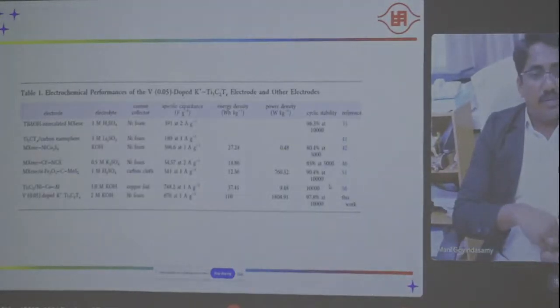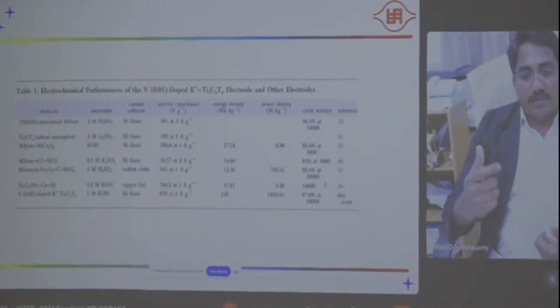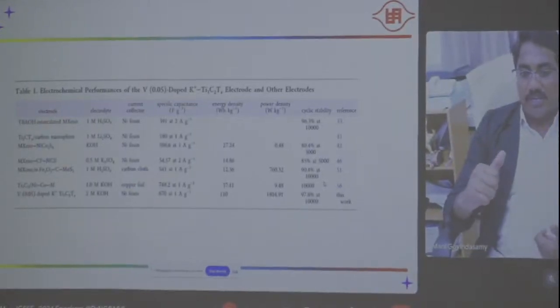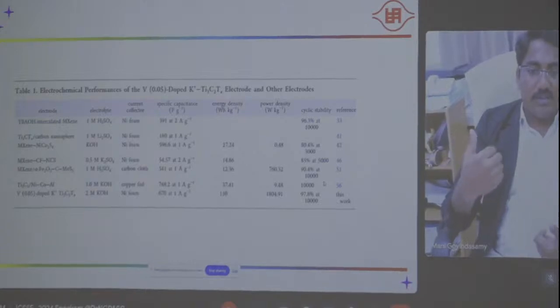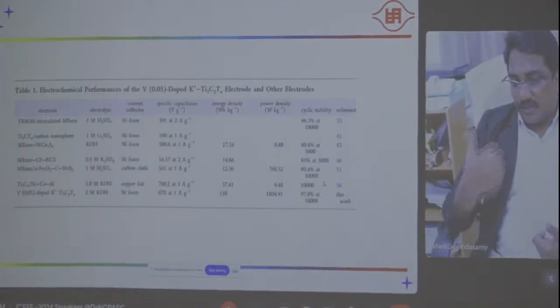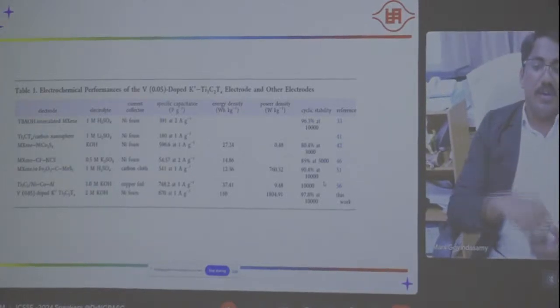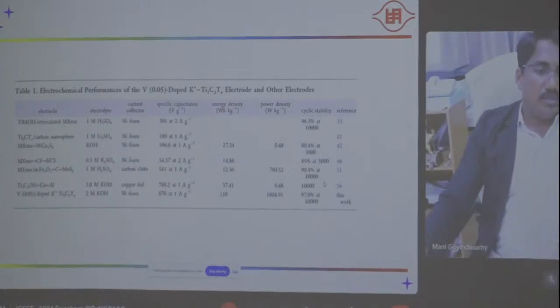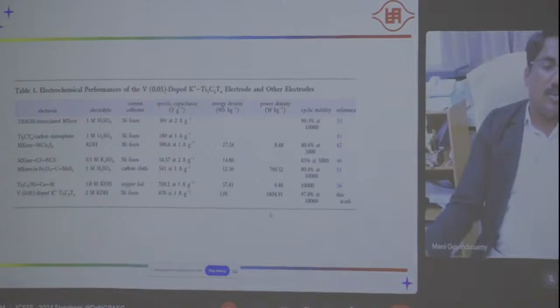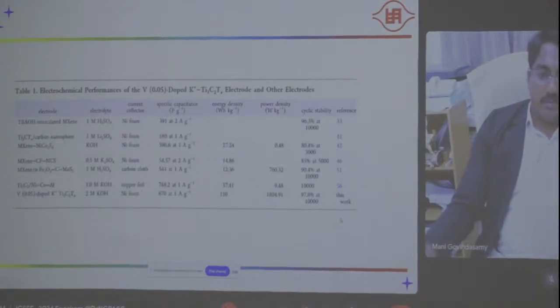So in this work, we develop, for example, a power density of more than 1800. Around 10,000 cycles, it gives 97.8% cyclic stability. In this work, we use KOH. For example, we use nickel foam as a substrate.